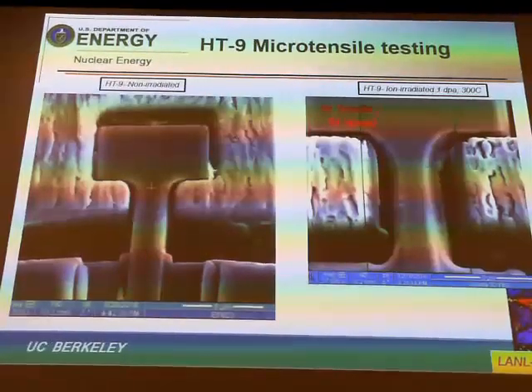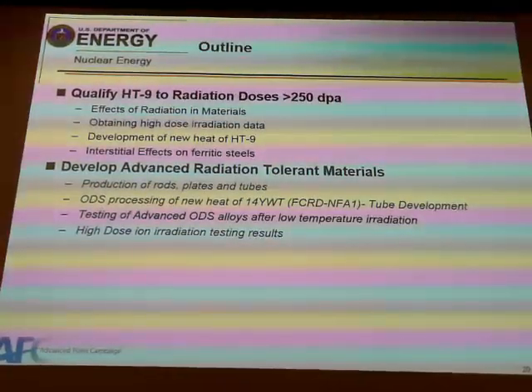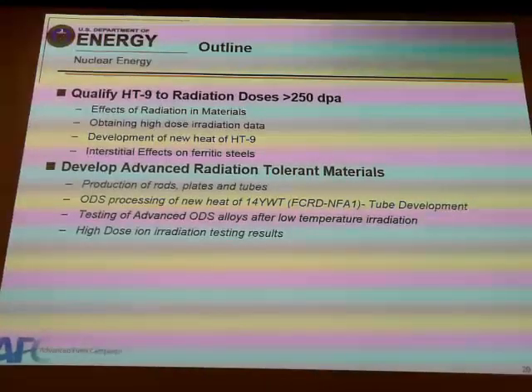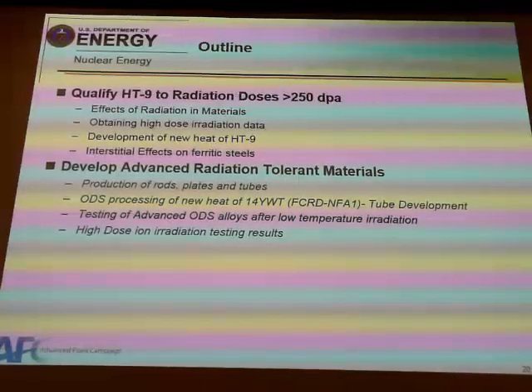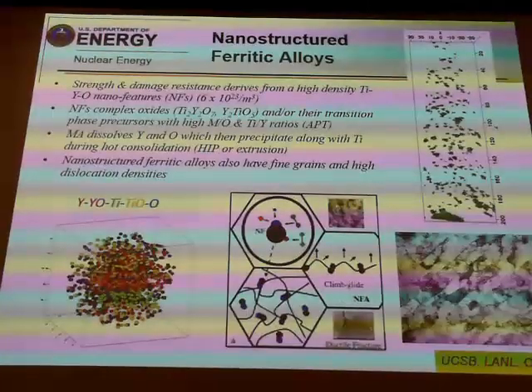So that's where we stand right now with testing some new improved heats of HT9. Hopefully by controlling the nitrogen content, we can push it to higher doses, especially in the lower temperature regime. The other area, though, is can we make even better materials by putting a fine oxide dispersion within the material. I'll summarize that in the next couple of slides, and also tell you where we are in making the heats, but also making them into actual engineering shapes, which is pretty difficult when you get to these improved radiation tolerant materials like this.